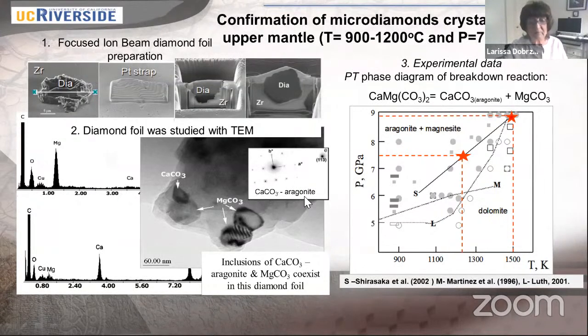When we went to that carbonate inclusion, you see here, we found that the carbonate inclusion consists of 2 sets of inclusion. You see the bar scale, 60 nanometers. We found there CaCO3 with aragonite structure. It's not calcite, it's a high pressure form of calcite with aragonite structure. We also found MgCO3, which is magnesite. We know that there is a breakdown reaction which produces CaCO3 aragonite and magnesite from CaMg(CO3)2.